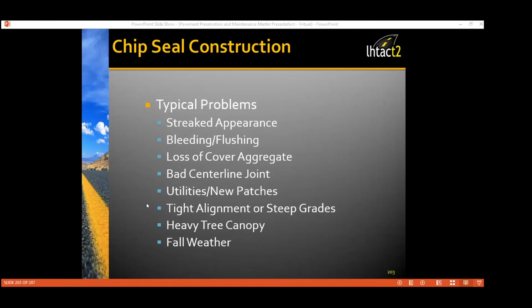Loss of the aggregate off of the surface is always a challenge, so pay attention to the oil content. A bad centerline joint can crop up and bite us if we're applying the asphalt and causing a bad centerline joint. If we've got a real tight alignment or steep grades, that may cause a problem. If we've got a heavy tree canopy, a lot of shade, like in a forested region of the highway, that might cause a bit of a problem as far as surface temperature of the roadway. And certainly fall weather: if we go too late into fall, then we're getting too cool and we won't get the chips to stick.